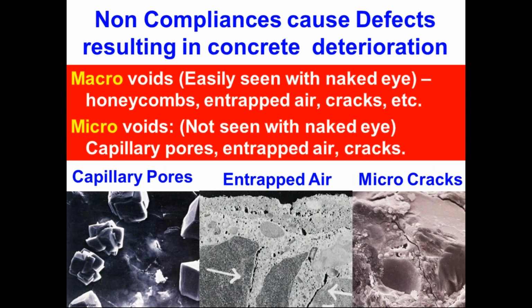Non-compliance causes macro and micro defects. When the capillary pores are large, the porosity is higher, the problem of durability is poor. But there are micro voids also caused.